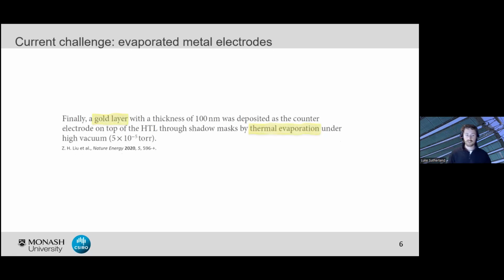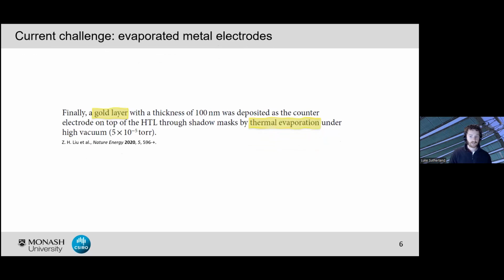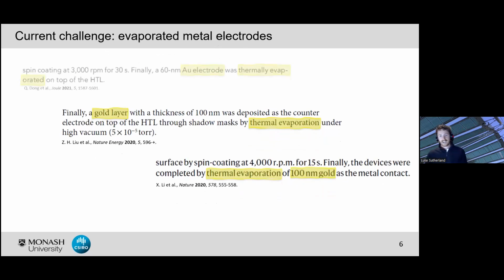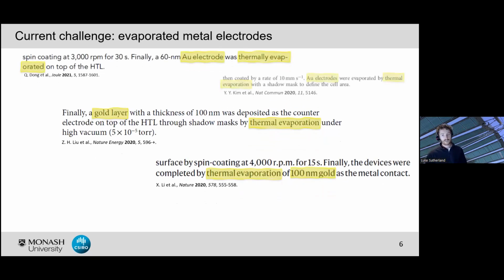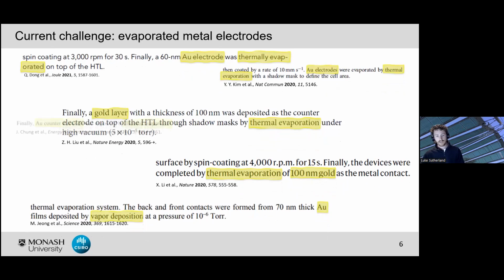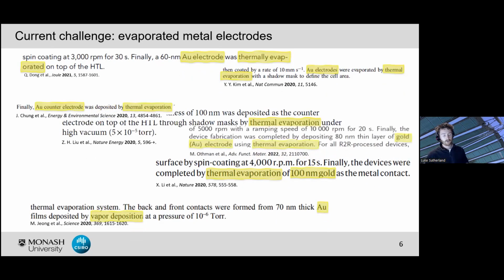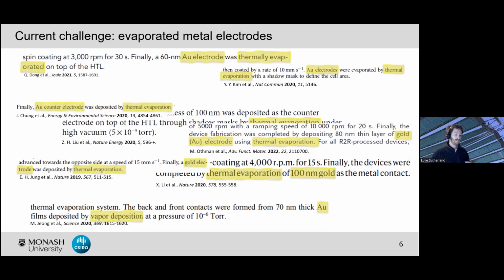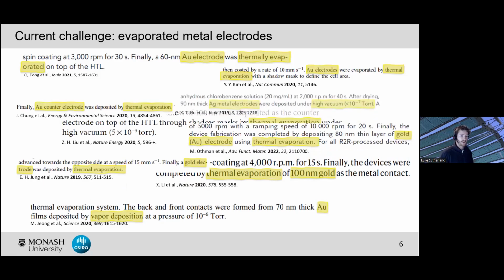If we take a very close look at these reports, we'll more often than not come across a sentence that goes something like this. So finally, a gold layer was deposited as our counter electrode by thermal evaporation under these high vacuum conditions. And this is the case for almost all of the highest performing perovskite solar cells, where a metal electrode, whether it be gold or silver, is deposited via thermal evaporation.